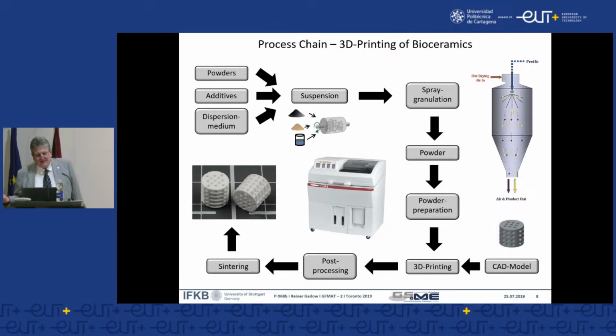So there is an option that the powder is coated with special additives. I will come back to this in a minute. And then we have to work with the typical engineering disciplines. The first is the CAD model. Yeah? And because of many reasons, we start with such cylinders, and we select a relatively coarse porosity, and this porosity is selected because of various reasons. And so typically, we know this since more than a decade, typically a medium pore size between 100 and 150 micrometers is perfect for the cell growth over a larger diameter or wall thickness. Therefore, it looks a little bit crazy. It is the macro porosity that is engineered.